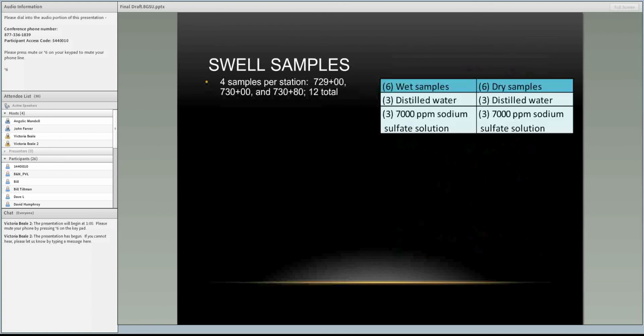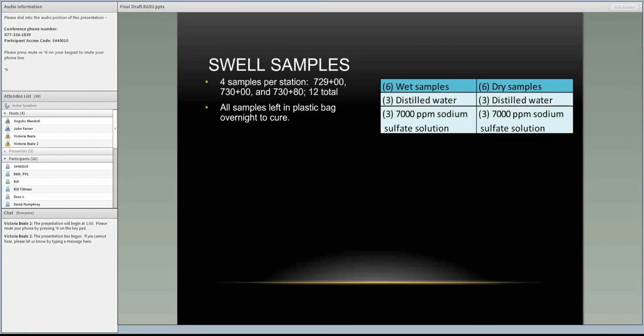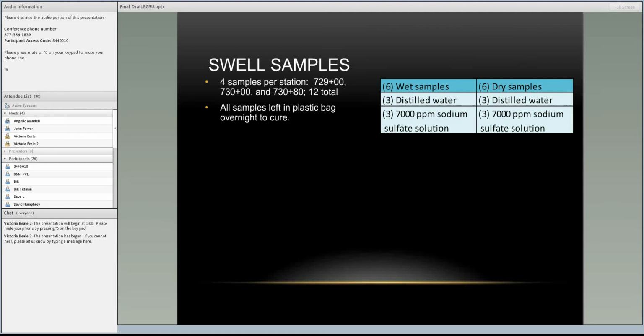We created samples here at ODOT, put them in plastic bags, and drove them back to BG, so they were left overnight to cure in the plastic bags. Then the next morning, the dry samples were taken out and measured, and then just left out and lightly covered to air dry for 3 days. After they were air dried for 3 days, we measured them again, put them in latex membranes, and then measured again, because the latex membrane does actually create some difference in the measurement. The wet samples, after being cured overnight, were immediately placed in latex membranes the next morning and initial measurements taken.